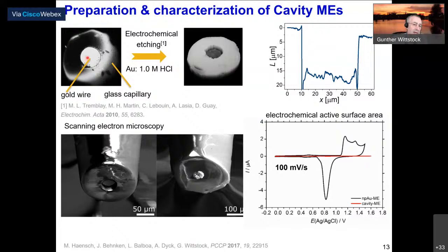So in order to take up our sample, we use cavity microelectrodes. That's been reported for quite some time. We were not the first ones doing that, but it has turned out in the last years to be extremely successful in my group for various applications. So we start with a gold microelectrode. We etch away the gold in HCl, so we get a recessed electrode. And that recessed electrode, the depth can be measured, and then we can use that basically as a pen or as a pot into which we fill a powdered electrocatalyst. And that could be platinum supported on carbon, it could be nanoporous gold, or as we will see in the second part of my talk, transition metal oxides.